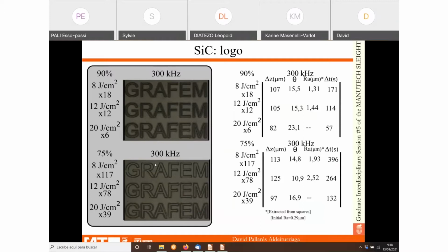And what's the interesting thing about this material? Well, here we have that for the same fluence, we have the same color, and this one only changes with overlap ratio. And please take into account that with PEEK, we have more of a grayscale change, but here it's more of a color change. We have some brownish tones that suggest that we should perform a proper color measurement, not only brightness.